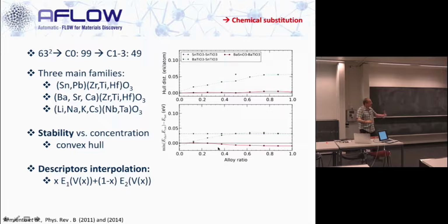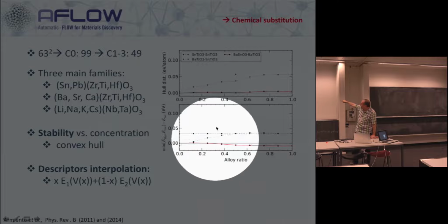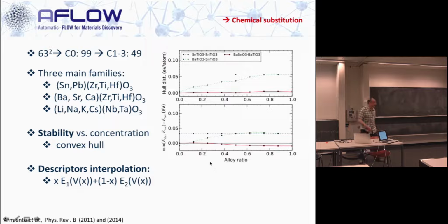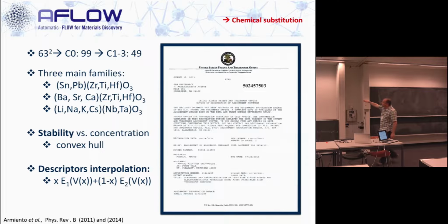So by tailoring this, you can actually find materials with some out-of-stability synthesis, far from the equilibrium synthesis, right? High-throughput synthesis or hydrothermal, anything that can go very far from stability, you can actually design a new material that is a lead-free piezoelectric. Okay, this was actually good. We found a few, more than one, and this was patented. That for a theoretician is good, right? We don't believe that we can patent anything, but it was actually good.